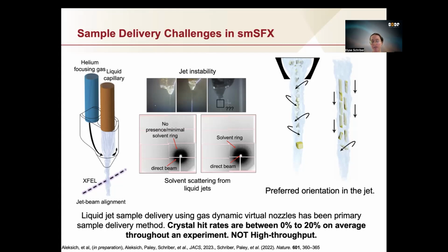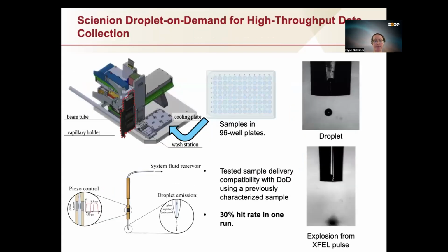Generally, the crystal hit rate, so how many actual diffraction patterns we're getting that we track via spot finder, is between 0 and 20% on average throughout an experiment. And what this has led to is a lack of high throughput data collection. And if we're going to turn this into a useful method for rational materials design and that can keep up with the rate at which materials are being synthesized, we need to create a high throughput method.